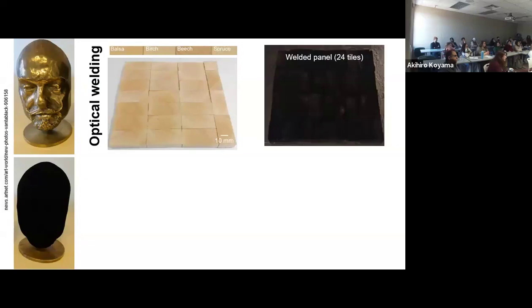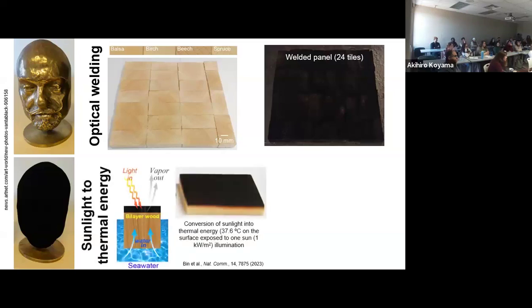And that wood, we found in a second follow-up article that was published, they weld optically. Like the same welding that we have been talking about when we have two pieces of wood. Here optically there is welding, meaning that if you take pieces of wood and you put them next to each other, after carbonization of the material, you are not able to distinguish the interfaces. So it's very nice because now we can talk about large-area construction materials.